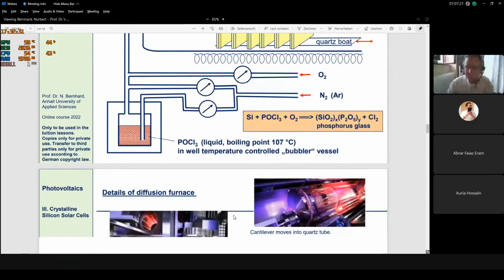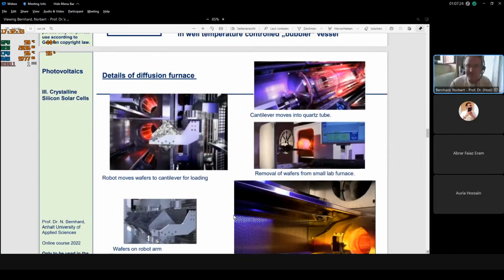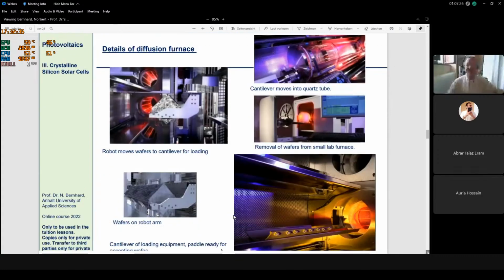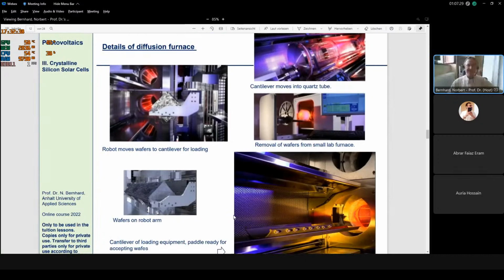Here are some photographs of such a diffusion furnace. We see in this picture a robot, and it's about to move the wafers towards a cantilever, which is used for loading them into the heated furnace tubes. You see this red color is from the big heat of these furnace tubes, in which finally the wafers have to be moved. And typically in such a furnace, we have several of these tubes above each other, typically 5 or 6 of these tubes.